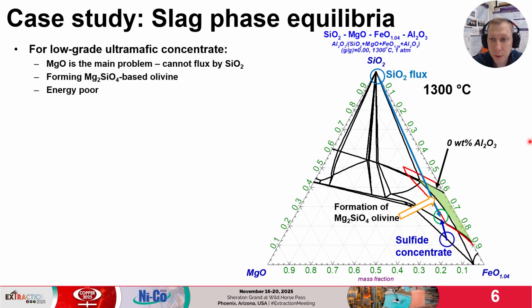From the viscosity point of view, it is beneficial to be further away from silica, close to spinel formation, but the formation of suspended crystals of olivine or spinel should be controlled. Small fractions of crystals can be beneficial for high agitated furnaces as described above, because it reduces the refractory dissolution into the slag.